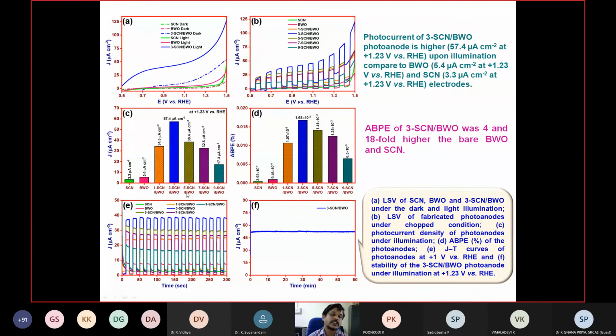Also, we checked the stability of the prepared samples. It shows excellent reproducibility. You can see we did a number of choppings, and still the photocurrent is maintained. And we checked the durability under long-term illumination. We tested for 1 hour. There is no appreciable change in the photocurrent. So we got excellent durability as well as stability for this prepared material.